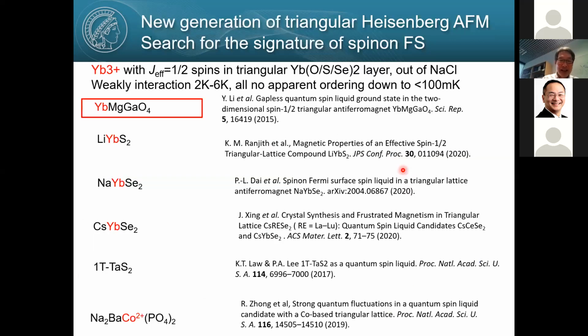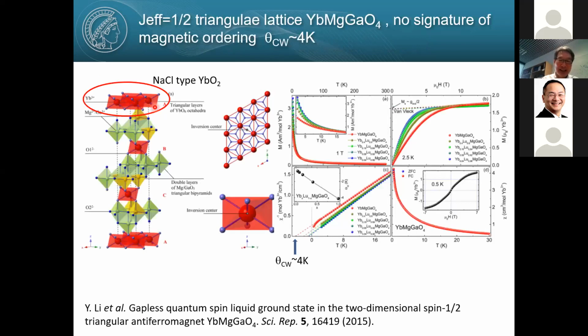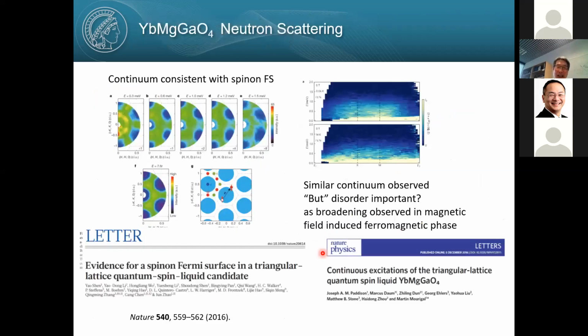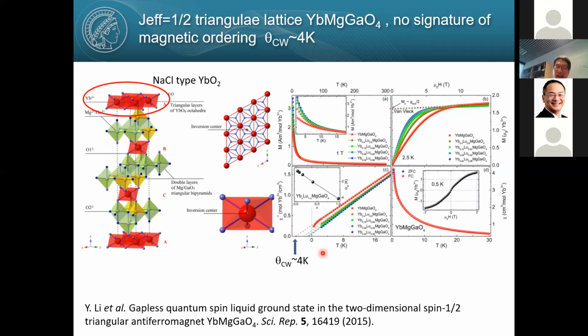And this compound, ytterbium magnesium gallate, has been studied quite enthusiastically over the last 5 years. There's a triangular lattice of ytterbium, connected by other elements, magnesium and gallium. Let me mention that in this layer you have magnesium and gallium, but for some sites you have a mixture of magnesium and gallium, giving rise to some sort of disorder. But anyway, measuring specific heat and magnetization, they didn't find any magnetic transition well below 100 milli-K. Although the energy scale of interaction is 4 K, and they claimed it's a quantum spin liquid. So no ordering down to 100 milli-K.